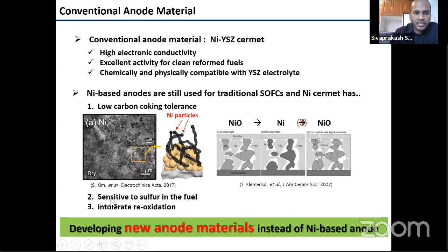The second disadvantage of using nickel as an anode material is that it's very sensitive to sulfur-containing fuels. For example, hydrocarbon, natural gas, or geothermal gases used in the anode contain a lot of sulfur-containing impurities. Even 1 ppm of sulfur present in the fuel causes metallic nickel to degrade very quickly. But in natural gas, the sulfur level is more than 50 ppm. So when we use alternative anode materials, removing nickel, we can use high sulfur content fuels.